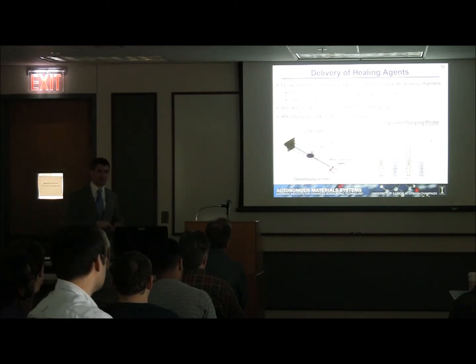Again, after that first testing, we can then close the sample and deliver our healing agents in through the backside. So the healing agents that we're using here, we're using epoxy resin, EPON 8132, and an amine-based hardener, Epicure 3046. And these are chosen because they're low viscosity components and they have a lot of heritage in the group, and they polymerize at room temperature, which is important for us. The stoichiometric ratio of these components is 1.9 to 1 by volume, resin to hardener. And to deliver agents through the sample, we're going to use a pulsatile pumping scheme inspired by previous work in the group by Andrew Hamilton.